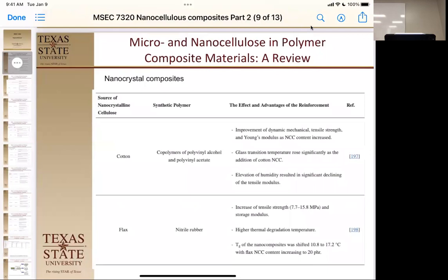And then they compatibilize it with polyvinyl alcohol and polyvinyl acetate. Again, the polymer has hydroxyls on it. The nanocrystals have hydroxyls on it. It's a good compatibilization. And they saw improved dynamic, tensile, and Young's modulus, of course. And they had a significant temperature difference when they added the nanocrystals. The glass transition temperature rose significantly by adding the nanocrystals.